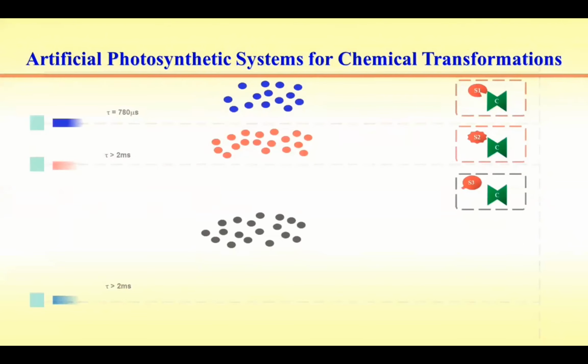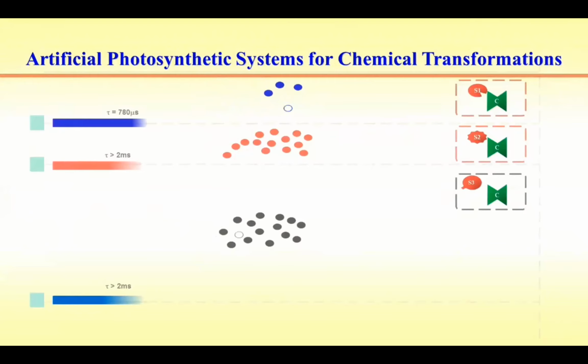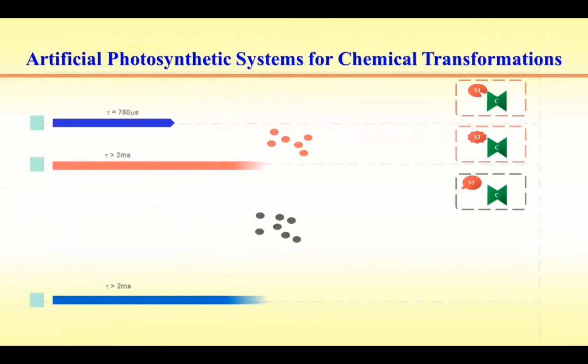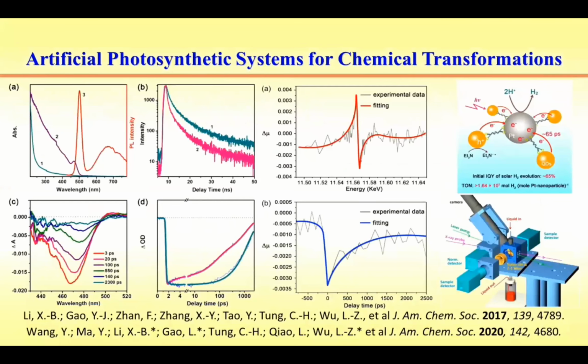Following the electron transfer, the reduced active sites can interact with the protons in solution. In this case, the longer the lifetime of the reduced intermediate, the larger the amount of hydrogen that will be generated from the reaction systems. Is it true that there is photo-induced electron transfer to the active site, and that the reduced active site interacts with the protons for hydrogen evolution?